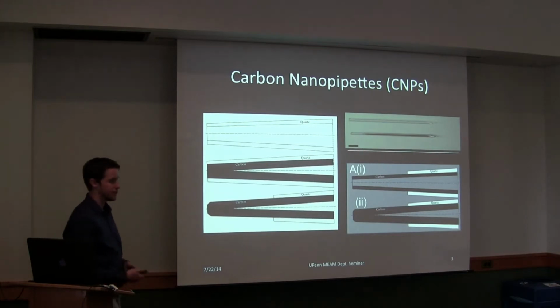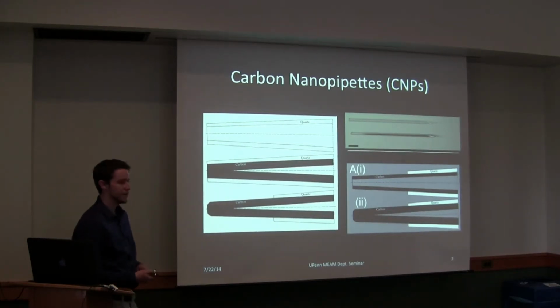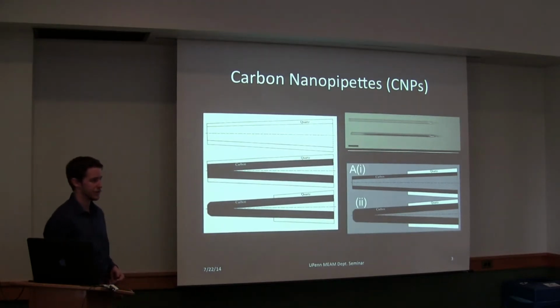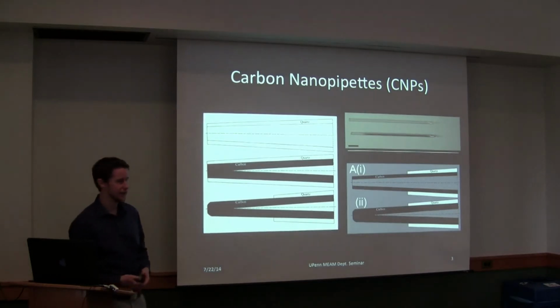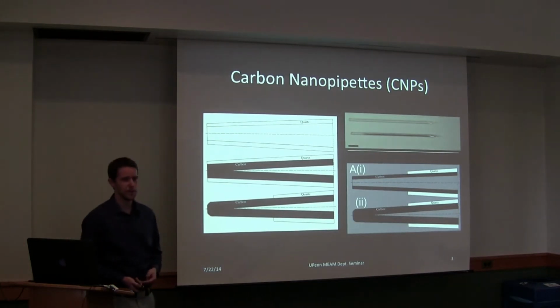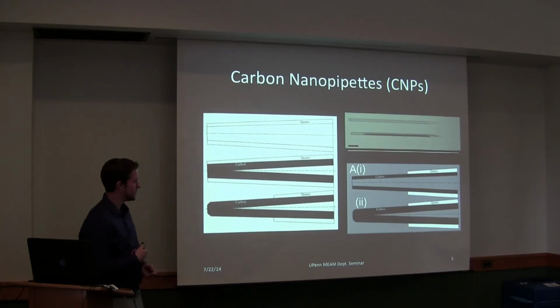We flow through argon and methane, and at high temperature, the methane decomposes and deposits carbon all along the interior surface of the pipette. There's actually a confinement effect that causes the carbon to only deposit on the inside surface of the pipette. Once we have the carbon deposited, here you can see it's darker after deposition, we can then put the tip into a wet hydrofluoric acid etch, which selectively etches the quartz. The quartz thickness near the tip increases roughly linearly with the length along the pipette axis.